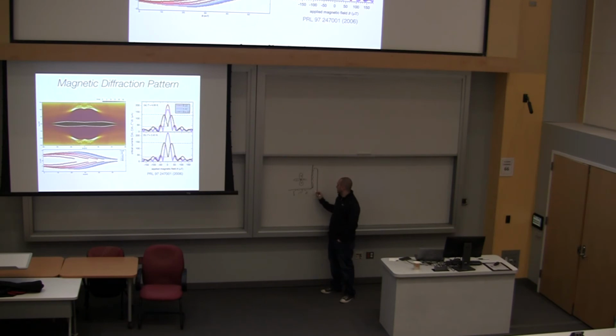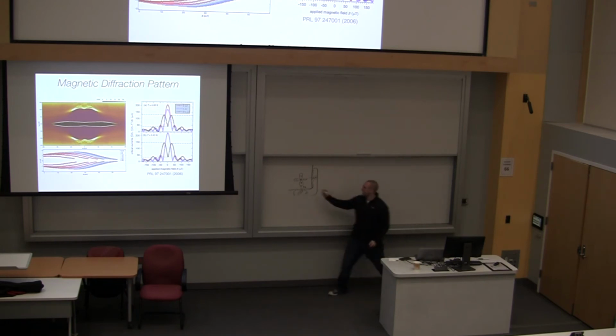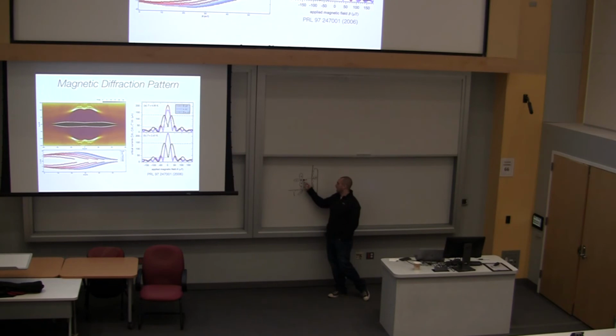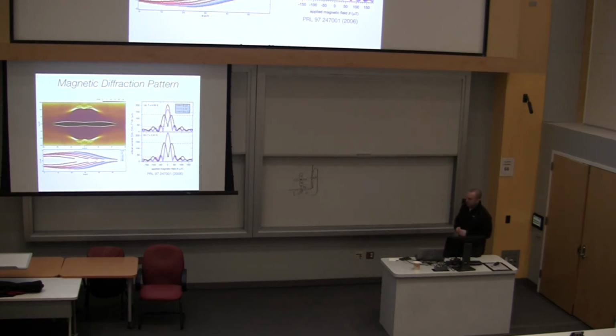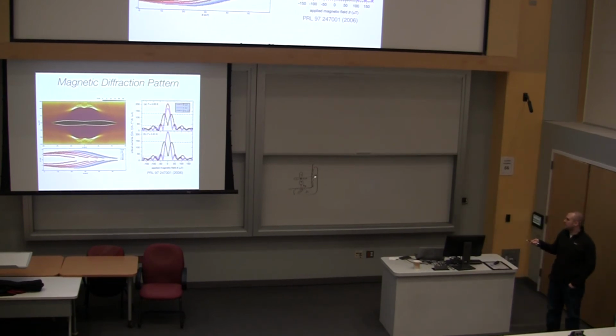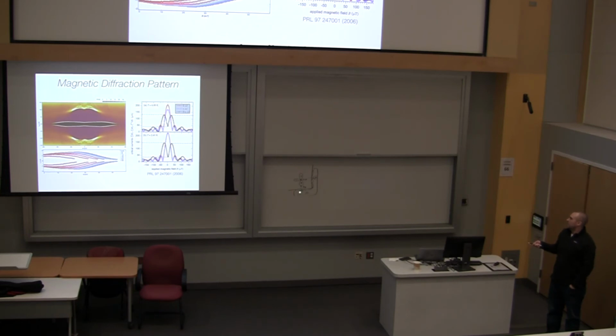So this is an aluminum superconductor, and my junction will be between this aluminum superconductor and the high temperature superconductor of this material. The Cooper pairs will tunnel preferentially along, say, the KY direction with a KY momentum. So they'll tunnel primarily into these positive lobes of the order parameter, whereas Cooper pairs over here would tunnel primarily into the negative lobes. So there's an out of phase component that comes from the fact that it's tunneling into two components of this order parameter. And this gives you destructive interference at B equals 0. So if there were perfectly equal amounts of Cooper pairs coming from this part of the junction and this part of the junction, you would expect this to go all the way to 0 for this perfect destructive interference. Now, if there's some inhomogeneity such that this one is stronger than this one, then you get a pronounced minimum, but not all the way to 0 critical current.